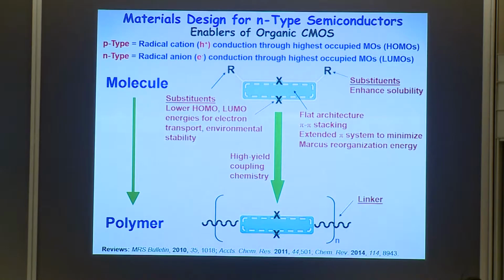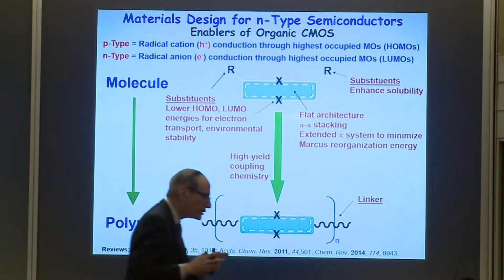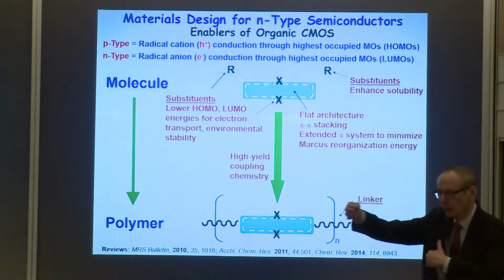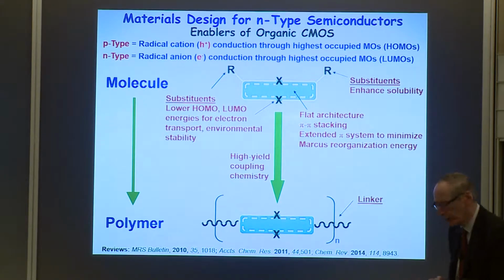And to do that, the idea was we're going to have a pi system, and think of it, we're trying to make something like a stack of poker chips, and the electrons are going to move through that stack from pi system to pi system, and also, of course, within the pi system. We're going to add electron withdrawing substituents to drop the energies of the LUMO. That'll make it very easy to inject the electrons from the electrodes, and substituents to make them soluble, a flat architecture so they'll stack, and rigid structures so this Marcus reorganization energy, when the electron hops from one molecule to the other, there won't be a huge reorganization barrier.